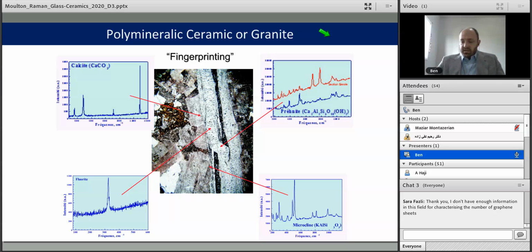For most of you, when you make a polycrystalline ceramic, or in this case, it's a photograph of a rock, a granite, there are many different phases there. And with one experiment, a Raman experiment, you can identify many different phases very rapidly. These spectra surrounding the photo are of a carbonate material, a fluoride material, and two different aluminosilicate materials. And you can see in these spectra there's a bunch of peaks at different frequencies, and we can use these to fingerprint the material.